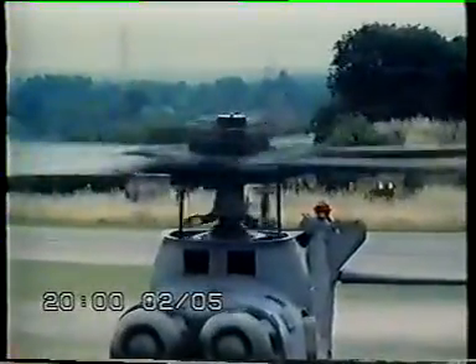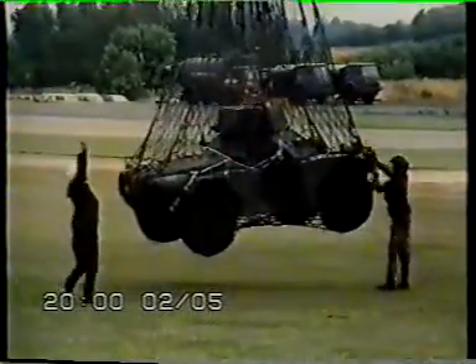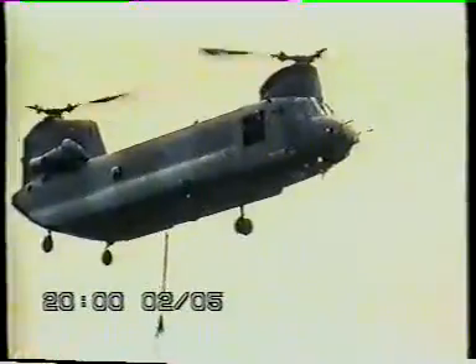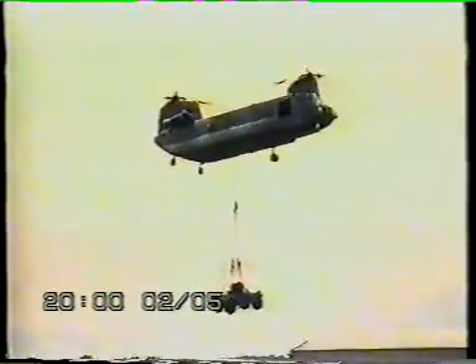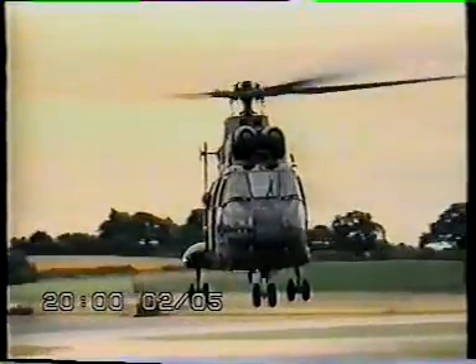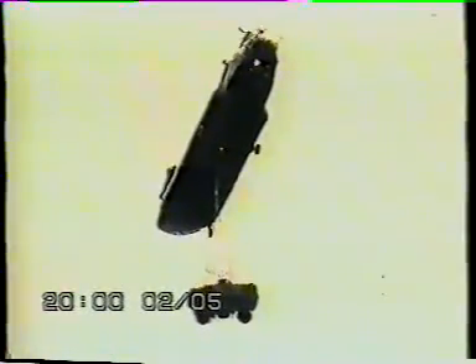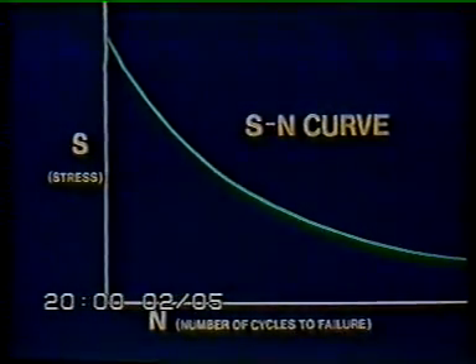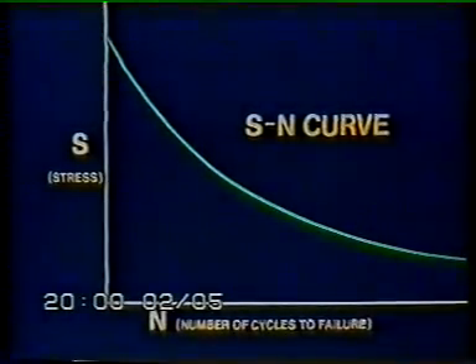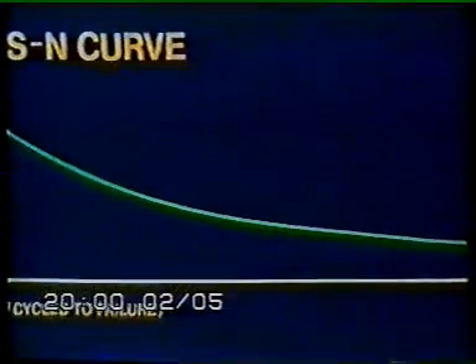Helicopters have major structural components which experience a relatively high number of load cycles. Even though the stress variation may be small, thousands of cycles will cause fatigue to accumulate quite rapidly. Particularly damaging operations include carrying large and heavy underslung loads, transition to hover, and flying sideways. Both helicopter and engine components have to be designed to operate under high cycle fatigue, at the right-hand end of the SN curve. Stress levels may be quite low, but repeated this frequently, they can cause damage.